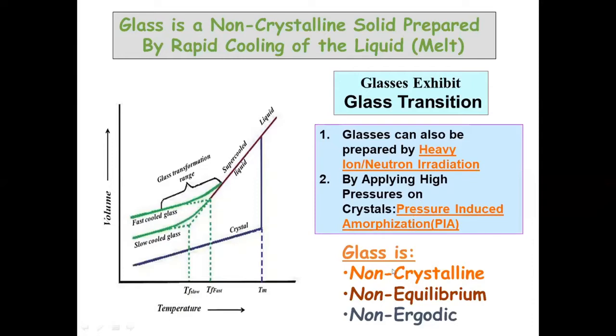So remember, glass is not crystalline. It does not have any regular arrangement of atoms. So if you do an X-ray diffraction or a neutron diffraction study of a glass, you will not see sharp peaks because Bragg's law is not applicable. Bragg's condition cannot be satisfied. You will see only broad humps due to the short range order, and glasses are not in the lowest energy state. So they are non-equilibrium. They have enthalpy which is higher than the enthalpy of the corresponding crystalline phase at the same temperature.